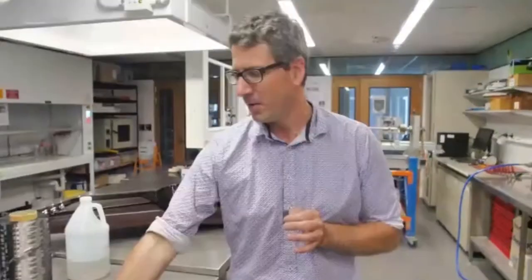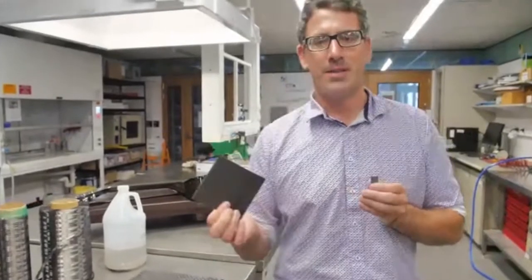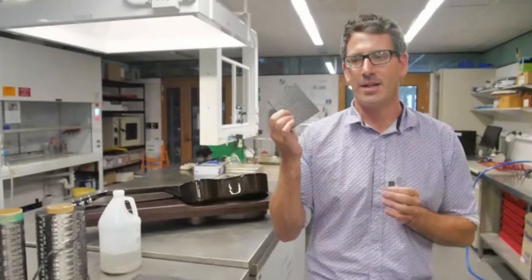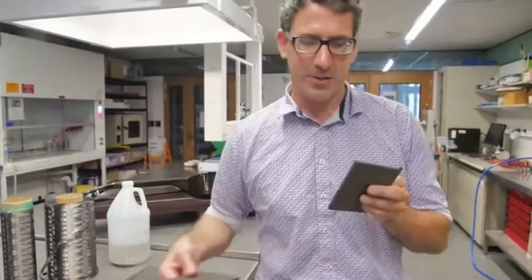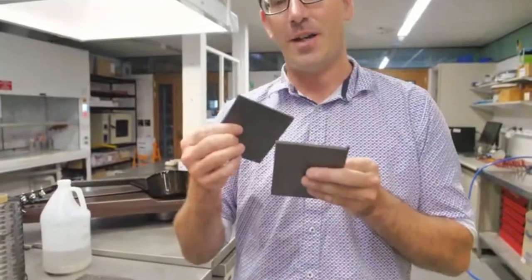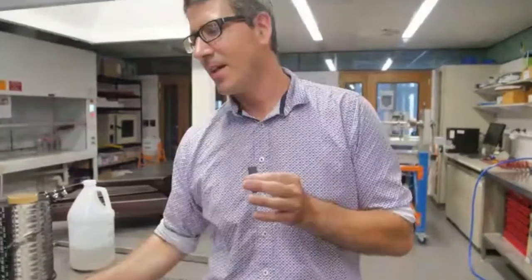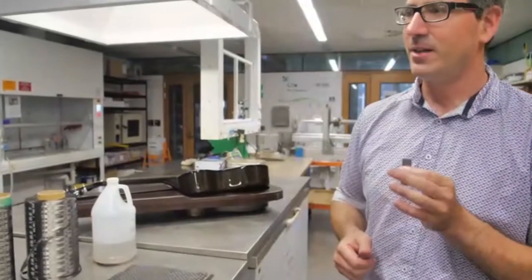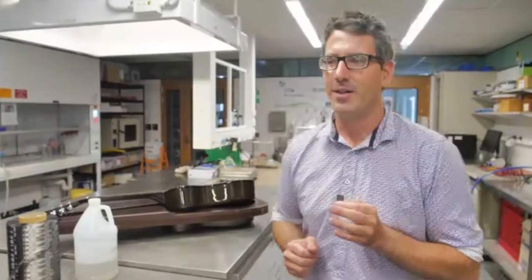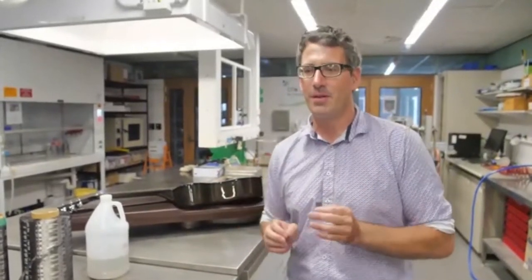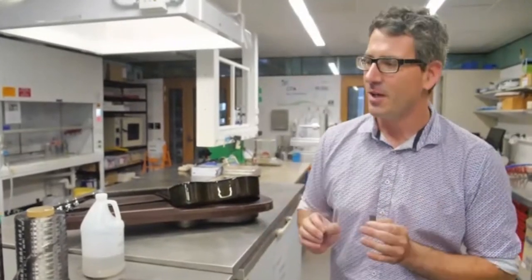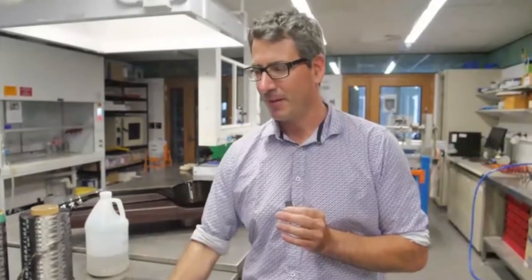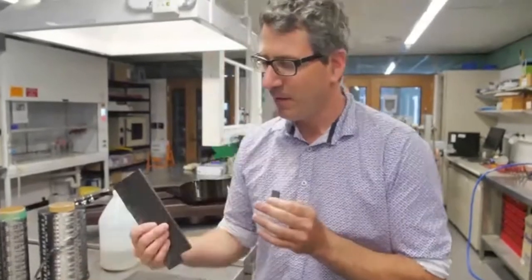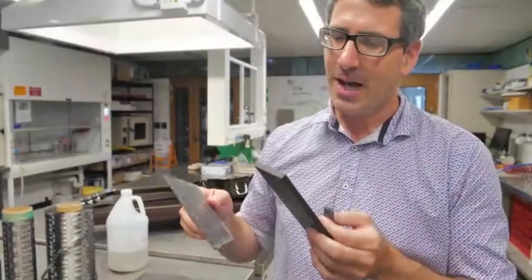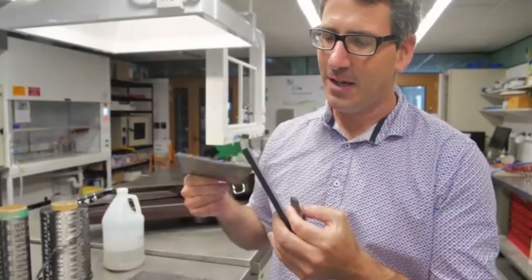What we end up with once we have cured our resin is what we call a green body. The green body is basically a polymer matrix composite made with the resin that has all the building blocks for our ceramic. And you can really hear it. I'm tapping the two green bodies, and you can hear really a plasticky sound. Now the next step is to convert the polymer into the ceramic, and this is done through a process called pyrolysis. Very similar to what we've seen in the fire lab, but this time with the strict exclusion of oxygen, we can convert the polymer into a ceramic. And once we have converted the polymer into the ceramic, we basically have our ceramic matrix composite. And now you can hear, it really sounds more like a ceramic than a polymer.